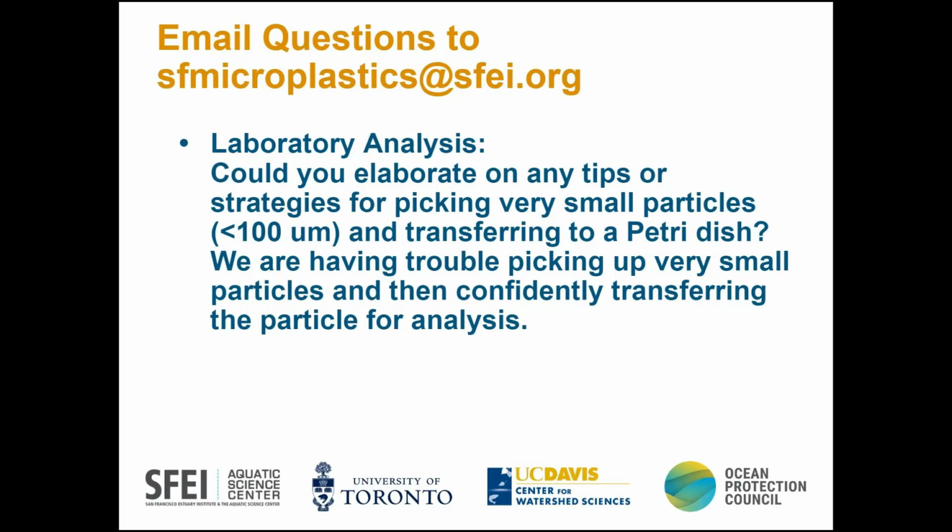We wet pick a lot of samples, so we'll pick spoonfuls of water with plastics in them. It helps a little bit to have water because you avoid the static issue. So if you have one pair of forceps, you can pick up a little droplet of water on one side of the forceps and then touch a piece of plastic with a droplet of water rather than actually attempting to pick up the plastic with both sides of the forceps. You can use the second pair of tweezers or forceps to scrape the droplet of water off of the forceps and onto the tape or whatever you're trying to mount on.